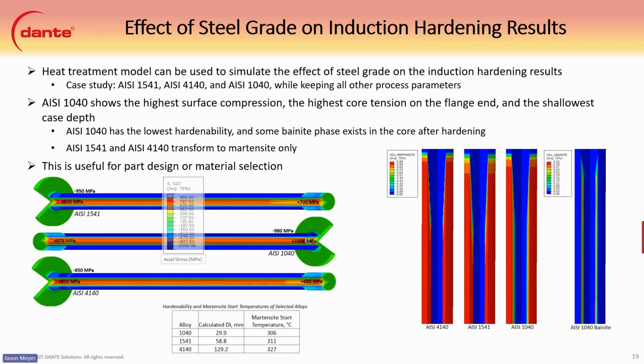So lastly, the last thing we did was they suggested that we try two different materials. We had the baseline 1541. We also looked at 4140 and 1040. All of these are 0.4 carbon, or just about. And you can see the table down below. They all have similar martensite start temperatures. They do have very different DIs as far as hardenability.